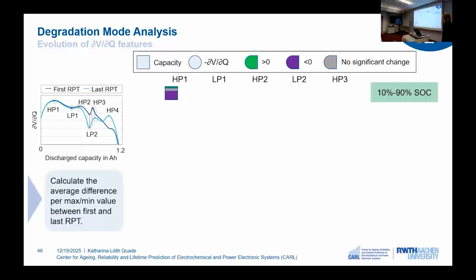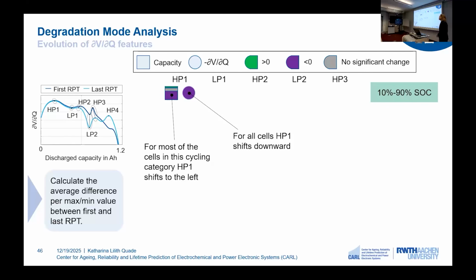And to analyze this in more detail, we again adopted our visual approach. Here we focus on the first and the last reference performance test, as you can see here on the left-hand side. And we also adopt a frequency-based approach, so we analyze the peak evolution for each cell individually. So this means for HP1, for most of the cells in this cycling category, HP1 shifts to the left. However, we can see that for some cells, it does not change significantly, and for some cells, it even moves to the right. And we can also include the circle that represents the DVDQ value, and here we can see for all cells, HP1 shifts downward.